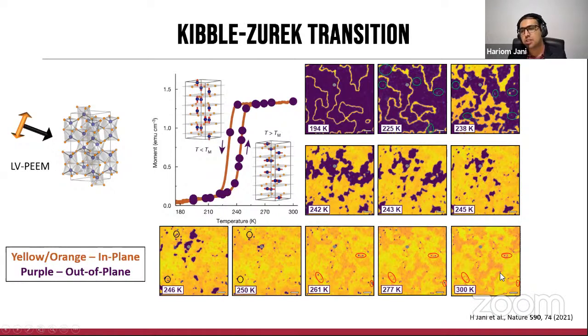So as a consequence, you would actually have the core objects which are having a certain color which match with the same color orientation as the low temperature state because they are both out of plane. Whereas the background would match because it's in plane with the domain walls of the low temperature state. So that is basically how we can clearly convince ourselves that they are of very different magnetic orientations.